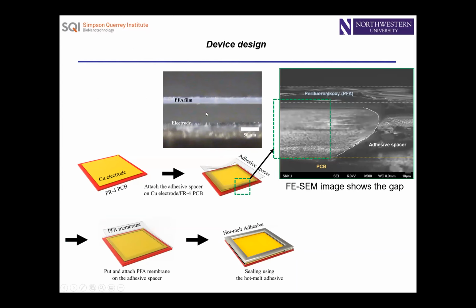The photo presents the polymer film, which is highly charged by triboelectrification, under the electrode with a certain distance, which is lower than 200 micrometers. So it is pretty straightforward to fabricate our device. We just assemble that triboelectric material onto the metal electrode and encapsulate the sidewall to hold the displacement. Just imagine if we keep applying ultrasound to the device, there will be constant oscillation, which might cause the device to fail. So to avoid that issue, we encapsulate the sidewalls to make the device work sustainably.